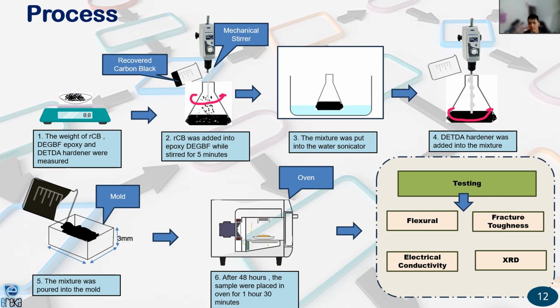So first, the carbon black will be mixed with the epoxy and then undergo the stirring process using the mechanical stirrer. After that, we will put it inside the water sonicator. Then we will add the hardener to make it become solid, and pour it into the mold based on the dimensions as already shown. Lastly, we will place it in the oven to undergo the curing process.